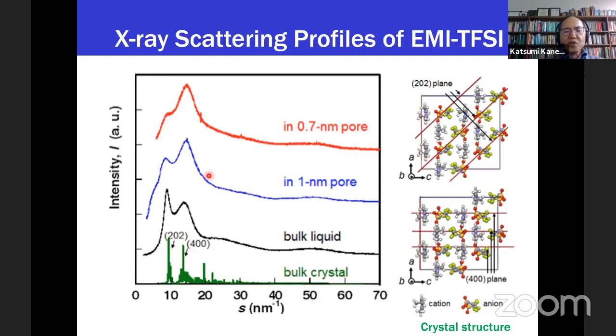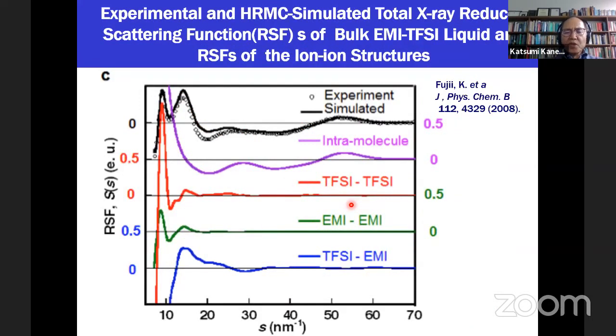This is the original data: the bulk crystal, bulk liquid, and confined EMI TFSI, with a very broad peak, changed from the bulk one. But we can analyze after several corrections, and then we can get useful information.